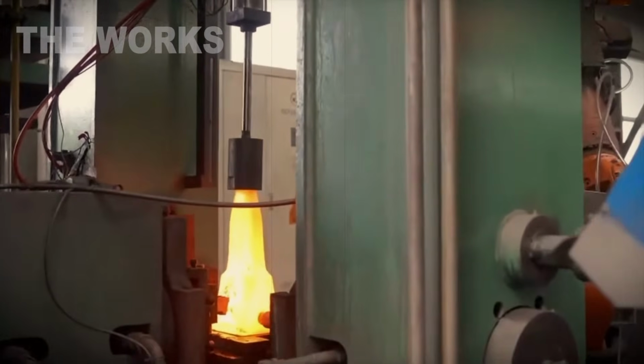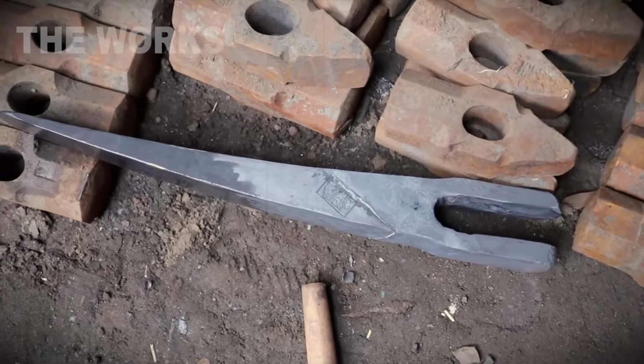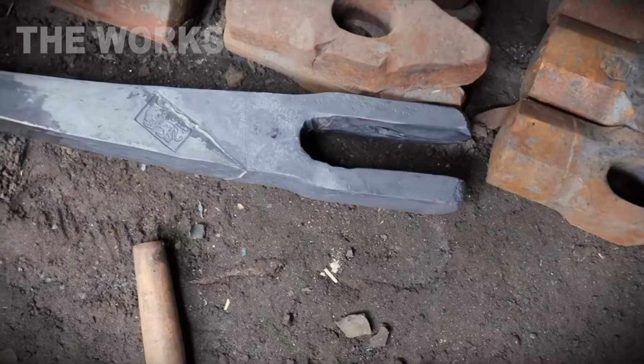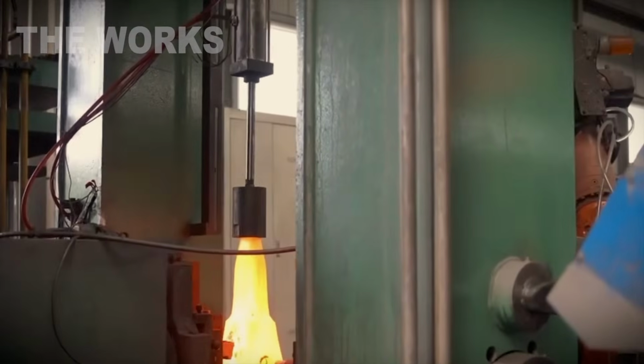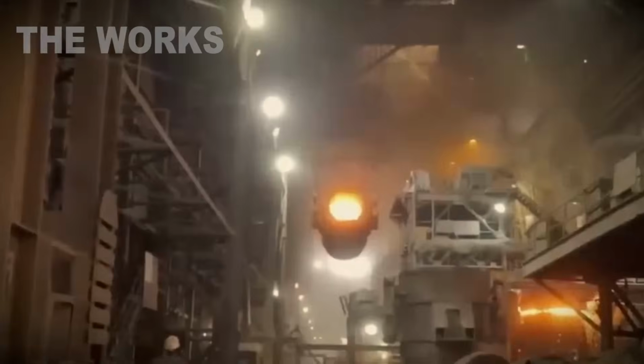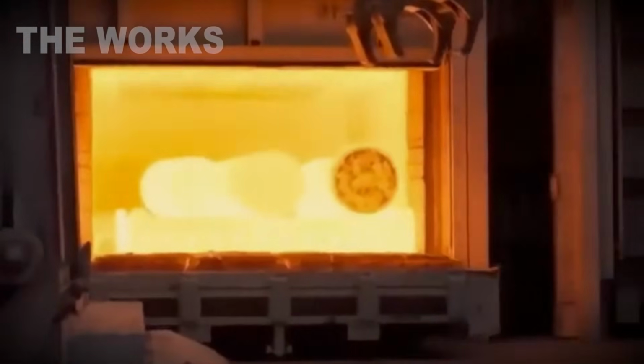The structure transforms into martensite. That's a needle-like crystal lattice, extremely hard. Hardness after quenching, 59 to 63 on the Rockwell C scale. That's harder than a file.